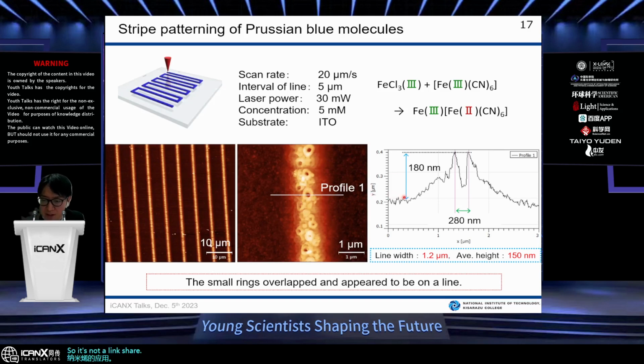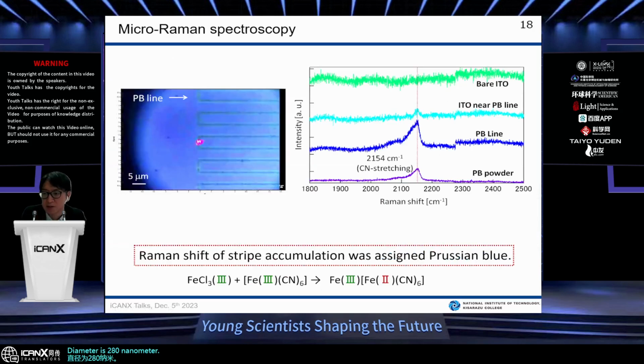These nanoring shapes have an average line width of 1.2 micrometer, an average height of 150 nanometer, and an inside ring diameter of 280 nanometer. Next, the stripe was measured by Raman spectroscopy, and the spectrum was similar to that of Prussian blue. This is the powder signal and the background ITO. This peak is similar to the Prussian blue powder. So these results indicate that a reduction reaction is proceeding.